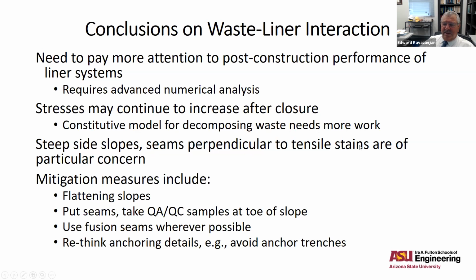Seams perpendicular to the tensile strains are of particular concern, but we have a number of mitigation measures that include flattening the slopes, putting seams in the geomembrane and taking QAQC samples at the toe of the slope instead of at the crest of the slope, using fusion seams rather than extrusion seams wherever possible, although they're not possible when you're patching an area where you took a sample for destructive testing.